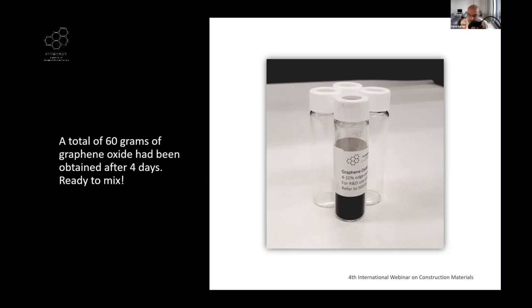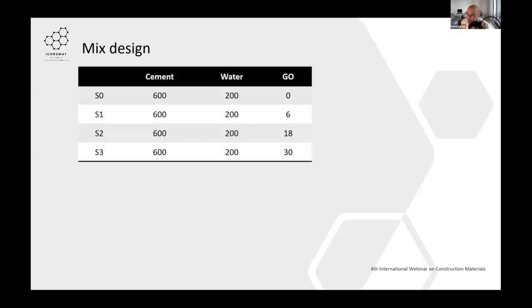Moving on, the concrete mix design. In the next phase of the study, we made cement mortar samples for the electrical resistivity test. The electrical resistivity test was chosen mainly to outline how good the product is for roadworks. Remember, the future roads are capable of charging electric vehicles on the way. So this table shows the mix design. Graphene oxide was added to the mix at ratios of 1%, 3%, and 5% by the mass of cement.